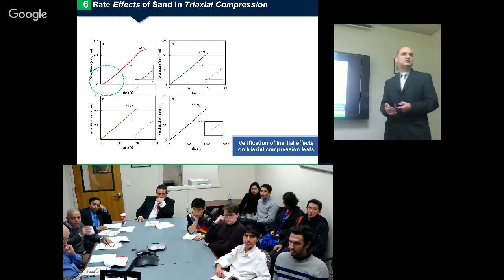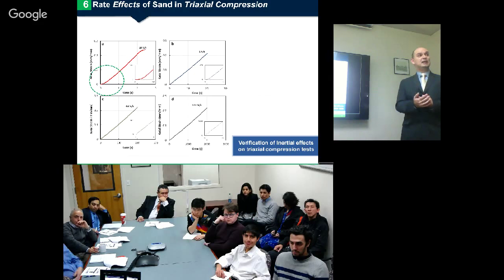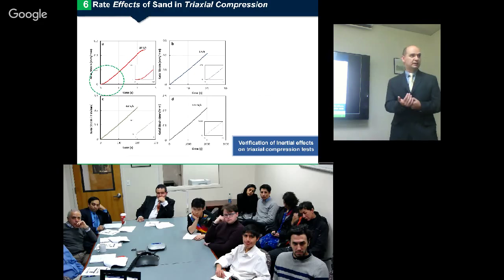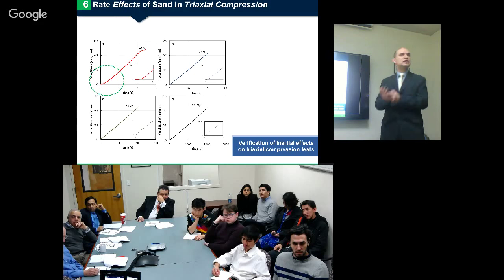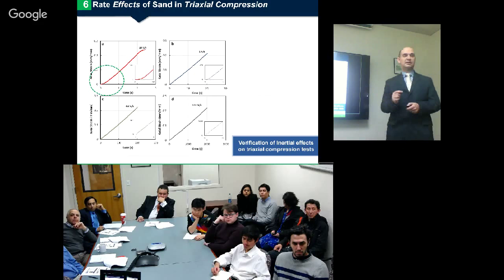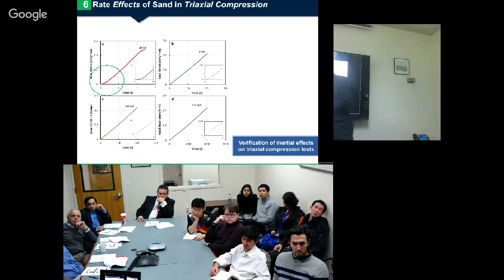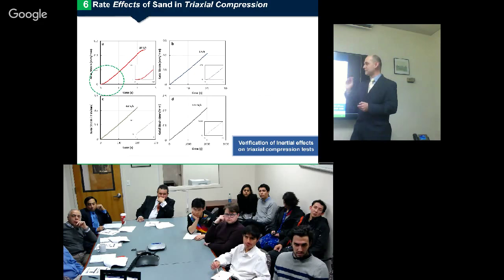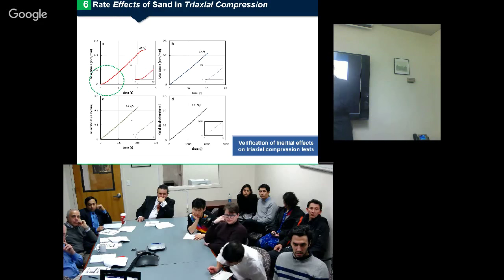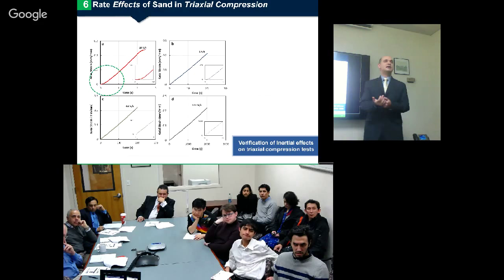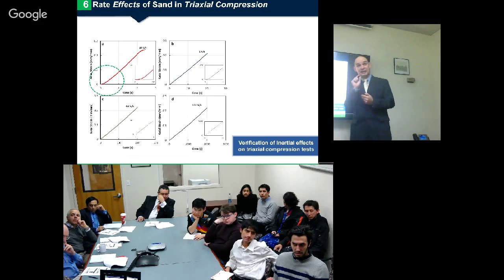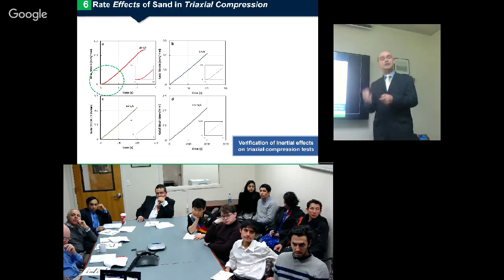One of the first steps was to verify inertial forces acting on the specimen when the sample is loaded. What we did was plot actual strain versus time. Ideally, the curve should be linear, but if we take a close look at the first half of a second, or the first 200 milliseconds, we can see a small concave path behavior that might be related to initial small inertial forces in the beginning. But for the rest, we have a very well-defined linear deformation.